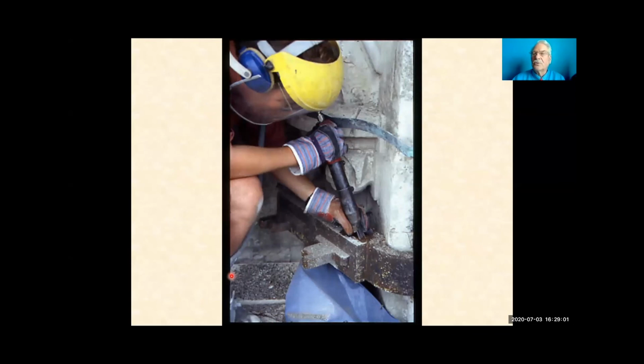This is one of the tools we love to use. We're very fond of these. They're called needle guns or descaling chisels, and they're about 10 to 15 little needles that vibrate. They're electric or pneumatic tools, and they simply knock off about 90%, 95% of the paint. And as you can see, the paint will just drop into a bag. You're not blowing it all over the parish and creating a hazard. Particularly useful for old lead-bearing paints because they don't break up into very tiny particles. They just drop into the bag.